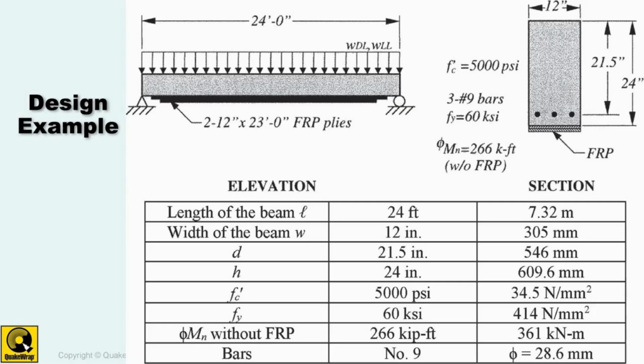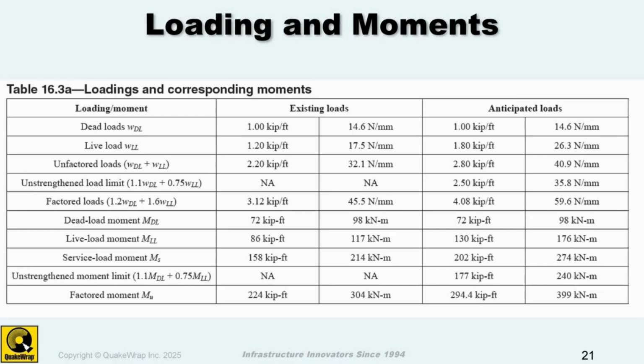So in this case, this beam that they give the designer is a 24-foot span, 12-inch wide by 24-inch deep, and they're applying 2 layers of fabric. You see, they have one layer and then another layer on top of it. So there's 2 layers, and the 5,000 psi concrete, 3 No. 9 rebars originally, and so you go through all of these steps that they tell you in this code. You follow one by one to get all of your design done.